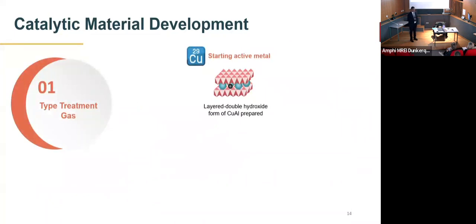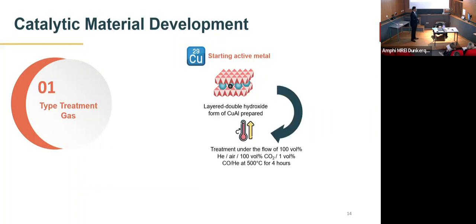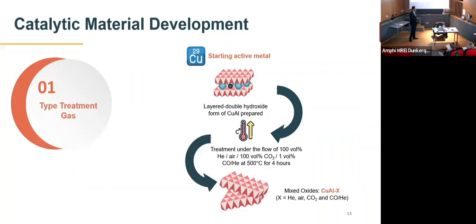In this study, we chose copper as a starting material based on the literature studies where copper metal was found to be active for such kinds of CO NO reactions. So first we synthesized the LDH structure of the copper aluminum LDH, and then treated it at a high temperature of 500 degrees Celsius under the flow of different gases like helium, air, CO2, and carbon monoxide diluted with helium, for 4 hours. At the end, the catalytically active component known as the mixed oxide is formed. In the further slides, you will see CuAlX as the nomenclature that we use to designate the different materials formed during the different treatment gases.